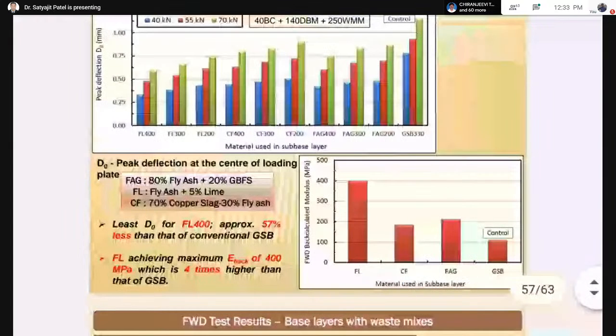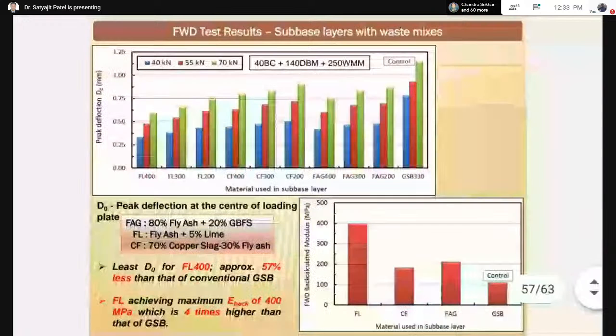These are some results of the FWD test. From the FWD test, we obtain directly the elastic modulus of different layers and also the peak deflection D0, which is obtained at the top of the pavement. So for different materials, different mixes, different thicknesses, you can obtain the stiffness value. The stiffness has also been obtained for different load intensities, like 40 kN, 55 kN and 70 kN load, applied through the FWD in the field itself.